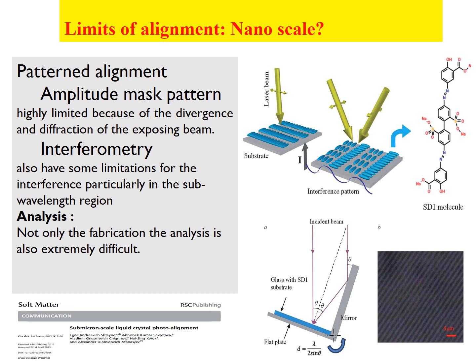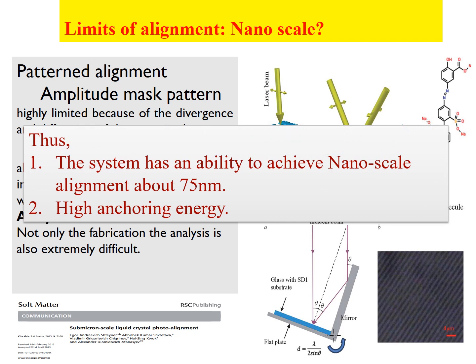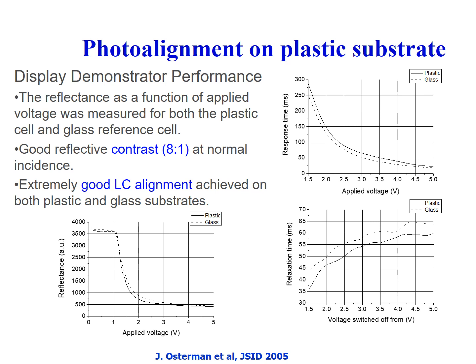The resolution is extremely high, which you can actually check by diffraction gratings. We come to the conclusion that the resolution is better than 75 nanometers, which is at the level of the optical equipment in our laboratory. Also, azo dyes can be successfully used not only for glass, but also for alignment on flexible substrates. All electro-optical characteristics are comparable with azo dye characteristics on glass substrates. Moreover, the temperature dependence is not very high as is usual for rubbing, so we can use a lot of different plastic substrates for liquid crystal alignment.